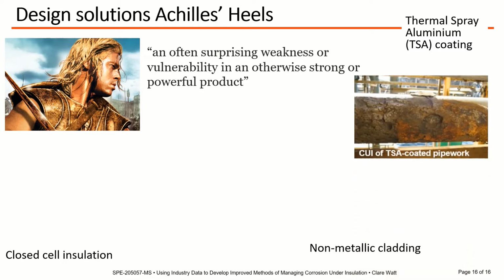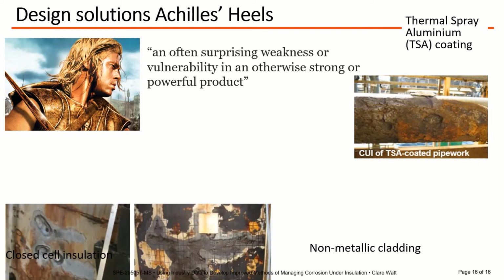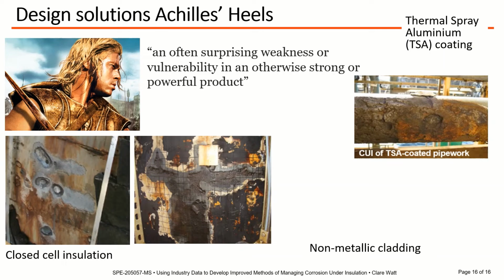So for example, TSA is vulnerable to occluded cell corrosion, which can be initiated by applying a too thick sealer or top coat, or anything else that forms a tight crevice at the equipment surface. And as far as we're aware, it's only been reported for marine environments as chlorides are involved. Closed cell insulation might not absorb water, but water can still get trapped at the metal surface and cause CUI. And the use of adhesives to fix the first insulation layer can not only accelerate CUI, but also cause it to occur in unusual locations, which might not be detected by prone area inspection schemes.